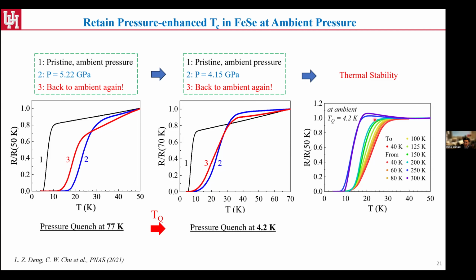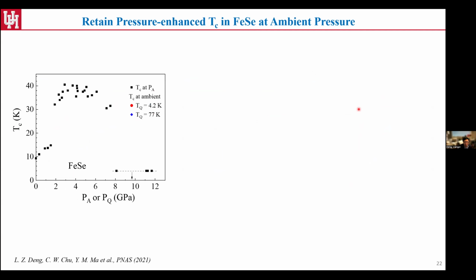That's also as we expected because of the thermodynamics. But I want to point out, even when we eventually went back to 300 Kelvin, it actually didn't really return to the normal phase, right? Because for the normal phase, the pristine sample, the TC is only 9 to 10, and now we still have around 20. So that still means this retained state is partially retained even when warming up to 300 Kelvin. So that's very positive along this line. So we want to understand better.